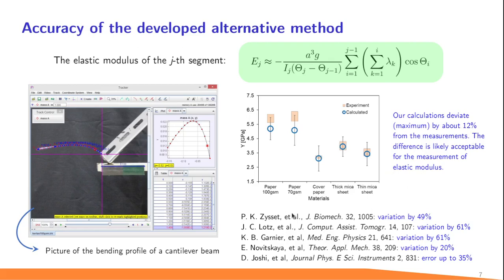For example, Zysset et al. obtained variation by 49% in measurement of the elastic modulus of human trabecular femoral bone using the nano indentation method. Lotz obtained variation by 61% for measurement of elastic modulus using the compression method. Garnier obtained variation by 61%, and by vibrating a cantilever using an electromagnetic method, Joshi et al. reported that a measurement of wire or strip can produce an error up to 35%. Therefore, the relatively small deviations in our measurements compared to the reference data are acceptable.